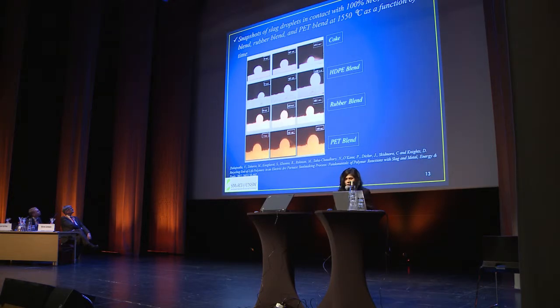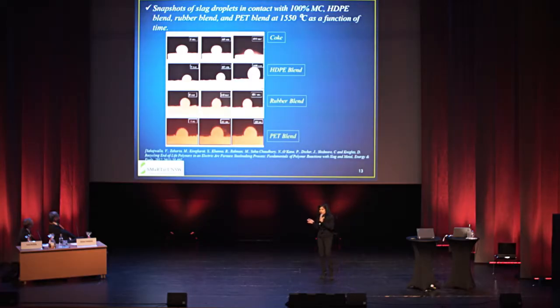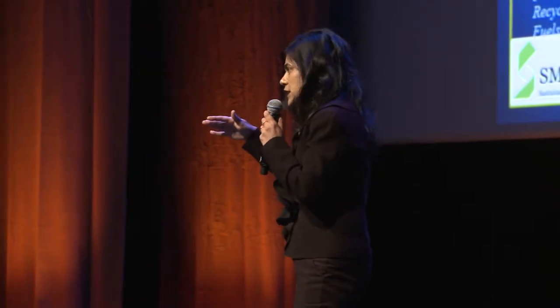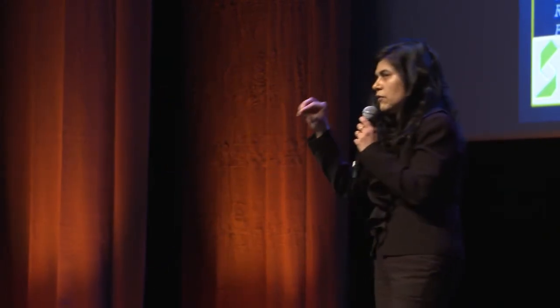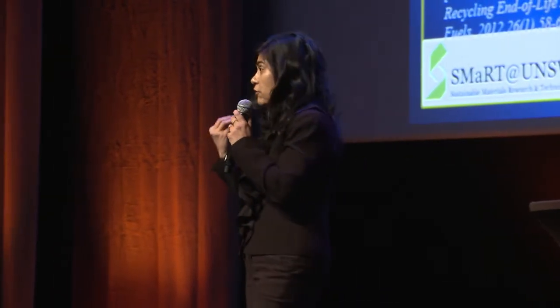What this picture is showing you is that if you look at the top layer, which is liquid slag sitting in contact with coke, traditional metallurgical coke that is used in electric arc furnaces in many parts of the world, and there might be other conventional carbons that might be used, and you now look at the ability of this liquid slag to continue to sustain the foam, what these pictures are showing, and time permitting I might play a video too, is that the slag volume is decreasing. We do know that if we are to sustain energy efficiencies and furnace efficiencies for an EAF, we need to be able to sustain that slag foaming.